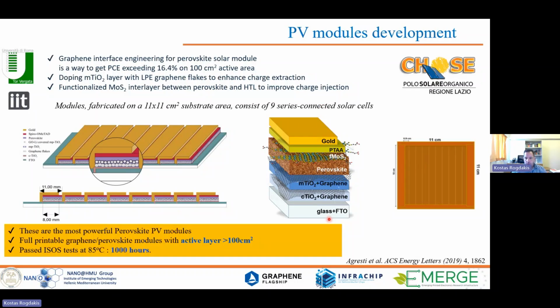This is a typical structure for the perovskite solar cells and modules. We integrated the functionalized MoS2 nanosheets between the PTAA and the perovskite, while we use graphene inks to dope the mesoporous titanium oxide layer and the compact one. As I told you, each module, 11 by 11 centimeters, consists of 9 series-connected solar cells. All this technology is in principle printable technology.